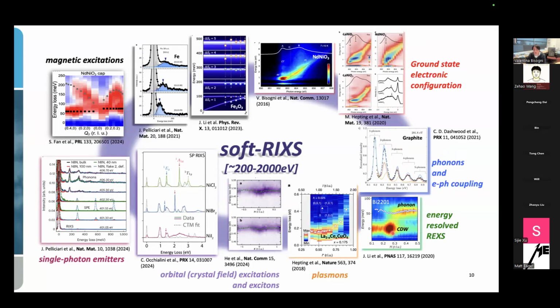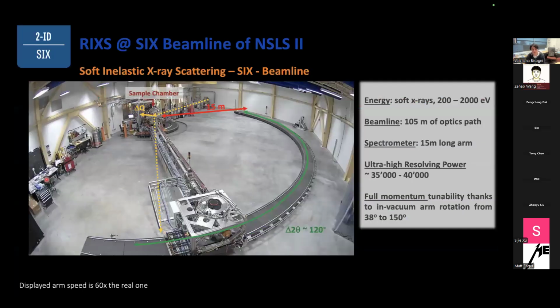We can look at very weak ordering phenomena, as was found, like CDW ordering in cuprates, by performing energy-resolved resonant elastic X-ray scattering and getting rid of all the other excitations that normally contaminate the elastic signal. We can access plasmons, so charge volume excitations, and their dispersion. Another important sector is access to orbital crystal field excitations and also excitons. And even more recently, it has been found that RIXS is sensitive to excitations connected with single photon emitters.